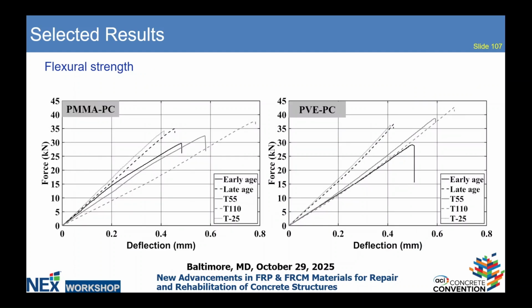Now, going on to the flexural strength, a similar kind of situation can be seen. The stiffness is decreasing, and the flexural strength is almost the same. Not much different, but the stiffness is decreasing. And the cold condition or extreme cold condition is increasing the stiffness as well as the strength.